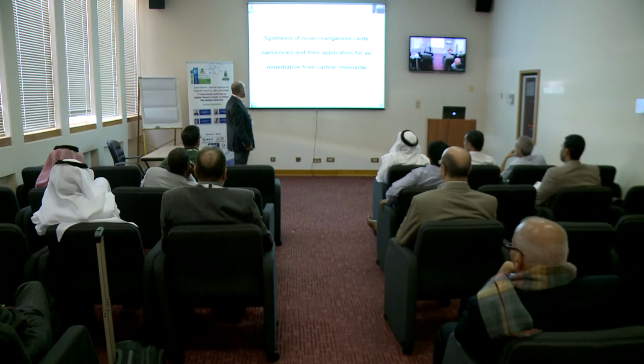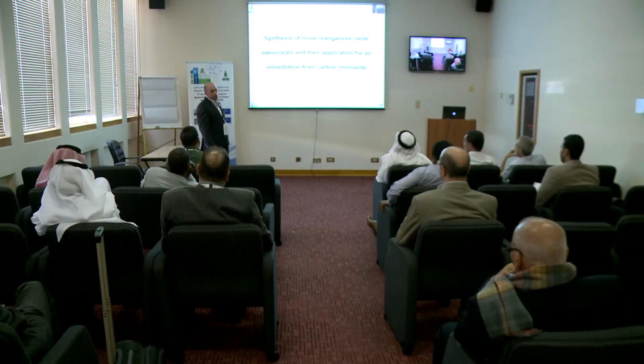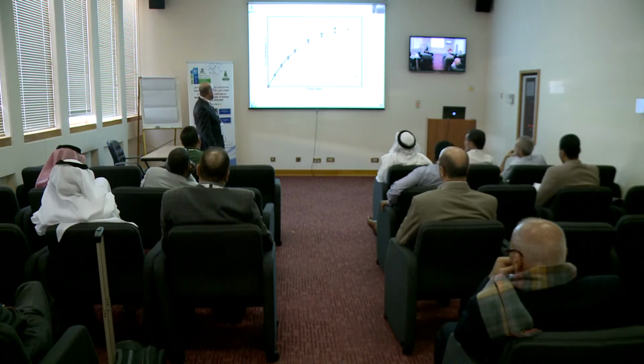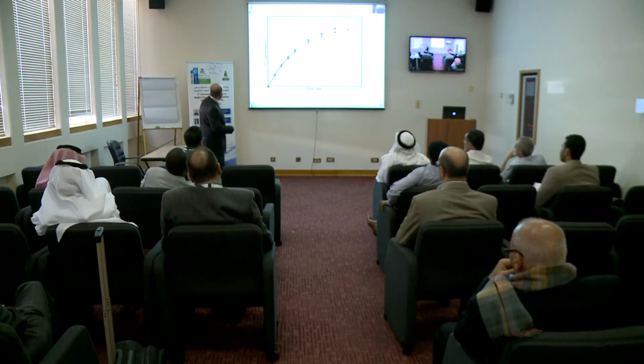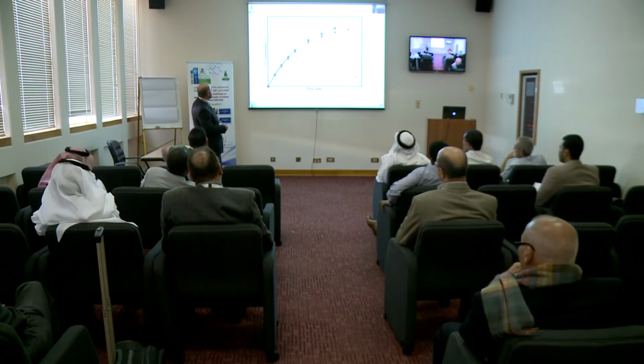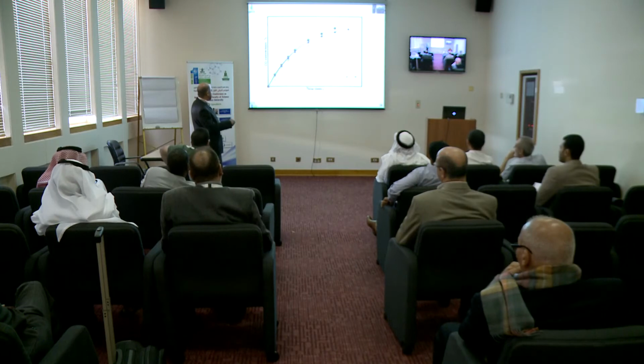the air environment. We use the manganese oxide nanocorals for the remediation of carbon monoxide. Basically, we change the carbon monoxide, which is a toxic gas, to carbon dioxide. I don't know if it's clear or not, but this is at different temperatures. At low temperature, the conversion is almost 1%, you have to believe me. When we increase the temperature, the conversion of carbon monoxide to carbon dioxide reaches around 100%.